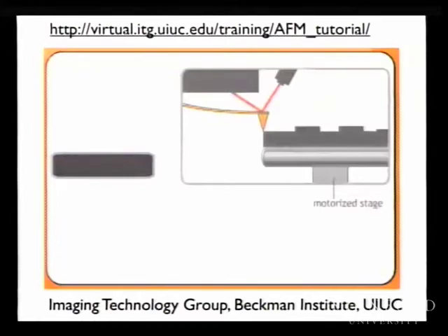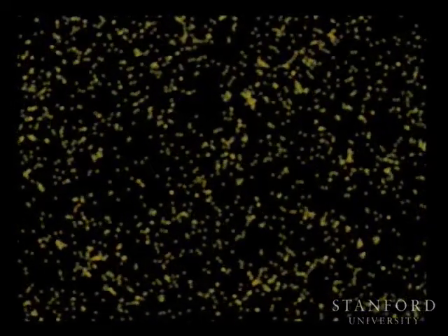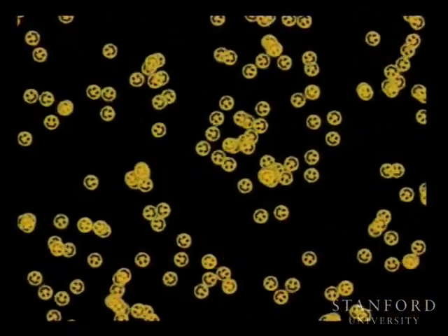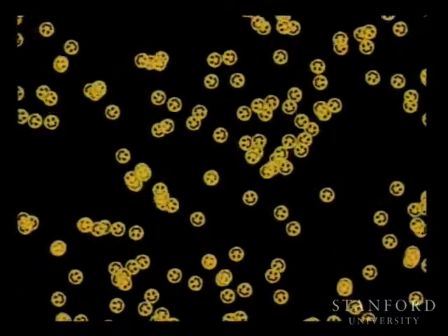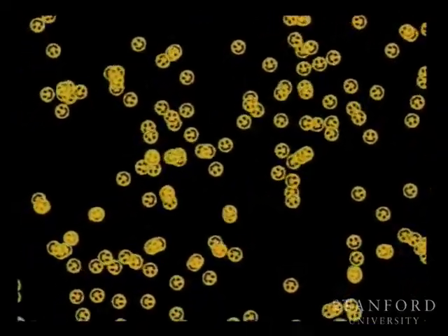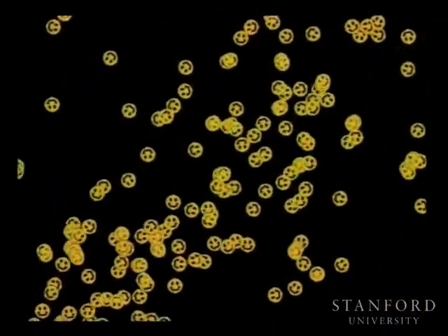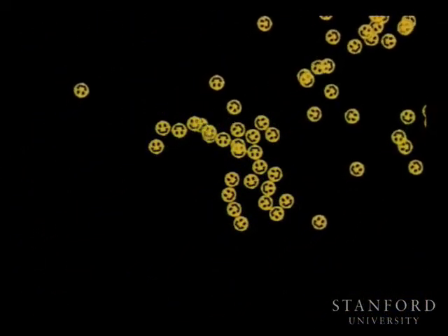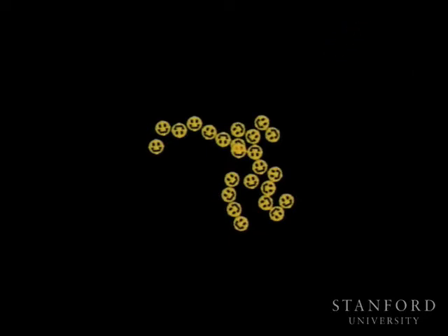Okay. All right. So this is again a completely fictitious simulation, but in a single 100 microliter drop of fluid, there are about 100 billion of these guys floating around, okay? So to use that very invasive imaging force, dragging the tip of a microscope back and forth, we have to immobilize them. So they're in a buffer, they're in a solution that has lots of magnesium ions. Those magnesium ions both stick to the DNA, which is negatively charged. The DNA carries lots of negative charge, and also stick to the negatively charged mica surface. Mica is this mineral you find in the ground. You can cleave it and get a perfectly atomically flat surface.